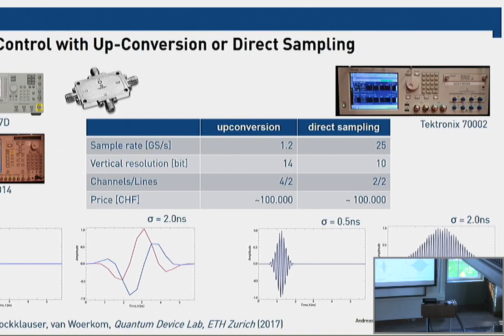pulse shape it in a Gaussian way, and you can play some tricks to avoid leakage into other states. For example, with this short pulse, we want to avoid that some of the pulse leaks into the resonator, and we could shape the pulse in a way that the spectrum at the resonator frequency was 0, so that these drive photons wouldn't show up as a measurement signal in the readout resonator.